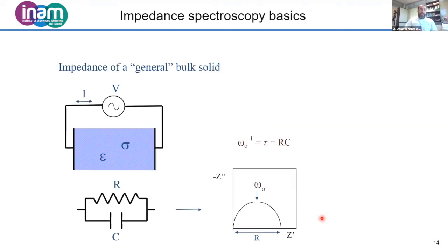If we continue with the typical elements and the response in impedance spectroscopy, as I mentioned, you can have a semiconductor where you have some type of conductivity, but it also behaves like a dielectric. So if you are measuring a bulk material, you will have this combination of a resistor and capacitor in parallel. A resistor and capacitor in parallel typically leads to an arc. This is basically what we were looking at previously. And this arc has a time constant, tau, which is the product of resistance times capacitance.